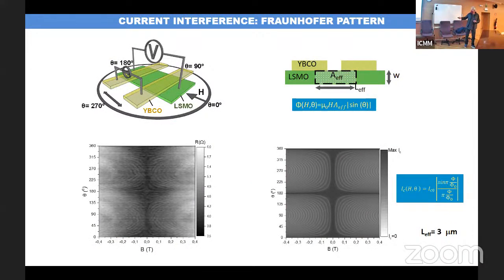The information that we get from these simulations is that we can work out the effective area of the junction. This is given by the thickness of the wire. This you cannot speculate. It is what it is, right? 30 nanometers. And then there is the effective length. Remember that the separation between the YBCO was 1 micron. And the effective length that we get is 3 micron. It's relatively long. I mean, we were a bit disappointed, right? But hold on a second.